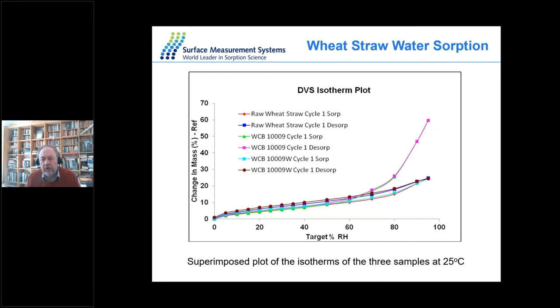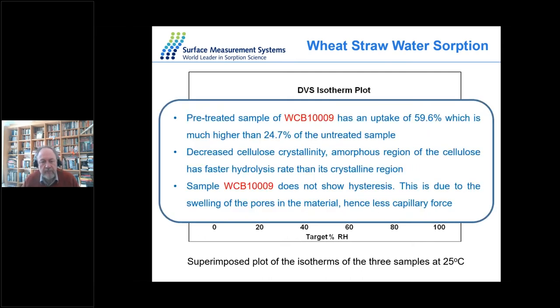And what that tells us is that that material must have much higher amorphous content, i.e. less crystallinity. So if we want to convert this material into biodiesel, where the crystalline domains will stop our process of dissolution, this is potentially quite important. So the pre-treated sample had a much higher uptake. That means it's got a higher amorphous content, therefore it's going to be more reactive. So decreased crystallinity and more amorphous regions.